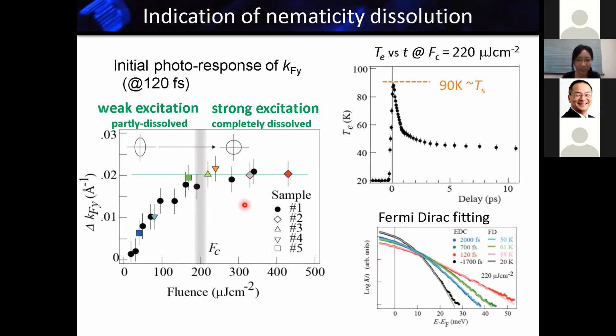In this strongly excited regime, we can measure the electronic temperature by measuring the Fermi edge at the Fermi level and fitting it with the Fermi-Dirac function. We can see that in this strongly excited regime, the electron temperature reaches 90 Kelvin, which is the transition temperature in the equilibrium state. So when you pump the system above this fluence, we can achieve the high electron temperature phase.